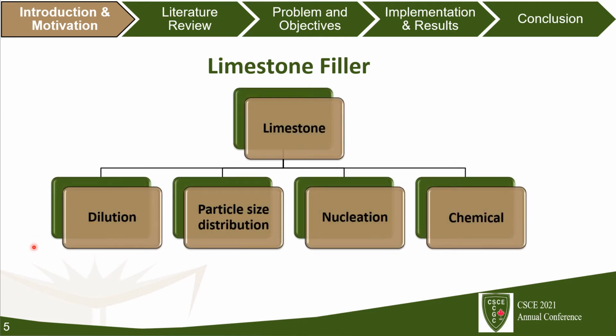First, it is far less reactive than cement, so we have the dilution effect. However, on the flip side, we can increase the particle packing depending on the size of limestone particles. Also, if we use fine limestone powder, we can get nucleation. Also, there is some research that limestone chemically reacts with the calcium aluminate hydrate and monosulfate to form calcium monocarboaluminate. And we will see later in the presentation how these 4 aspects come into play.